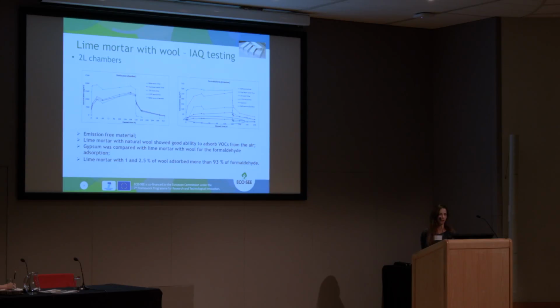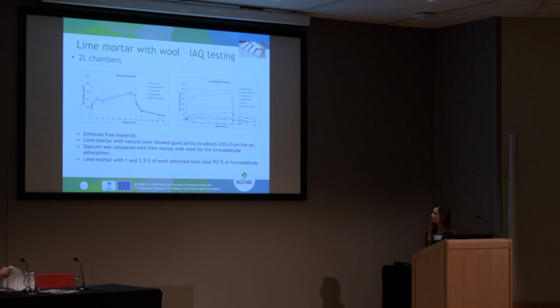This is one of my last experiments that I did, with lime mortar with wool. The idea is to improve even more the adsorption of VOCs by the lime mortars. So we know that natural wool has a good ability to adsorb formaldehyde. So why not combine the lime mortar and wool to improve the adsorption of formaldehyde? And we observed that, for example, if we have a polluted room with 300 ppm and we apply this material, the concentration will be decreased by 93%. So that's good.